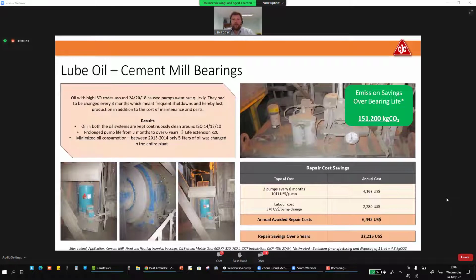To give you an example here, and this is a cement mill trunnion bearing on an Irish plant, a customer of mine. We had a very contaminated system. The pump was only lasting 3 months and had to be changed, with cost, of course, and stoppages. It cost a lot of money to replace the pump, simply because the oil was dirty. We put in our filter, which I'll explain a little bit later, and by cleaning the oil down to 2 to 3 times cleaner than new oil, this pump lifetime went from 3 months to over 6 years. So a life extension of over 20 times.